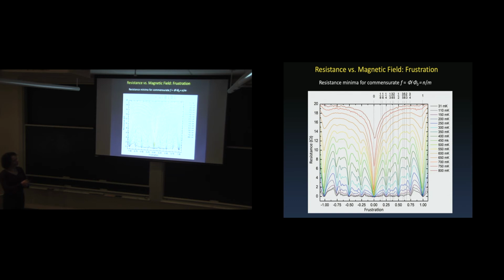And then as I go away from zero field, my resistance increases. But then as I go to quarter filling, it decreases again, because my vortices are interacting, so they're pinned. Then my resistance increases, and then, I don't know, this is like 2/5 or something. I get these little dips in between, and then at half filling, I get a very strong pinning again, so my resistance goes down. Same thing at 3/4. And then kind of miraculously, I've increased field here, right? My field at this point is bigger than my field at this point, and yet I have a lower resistance there because at one vortex for every plaquette, I have such a strong lattice that it's strongly pinned.